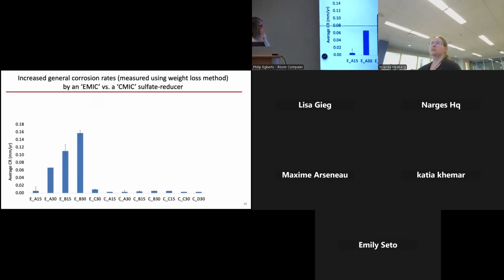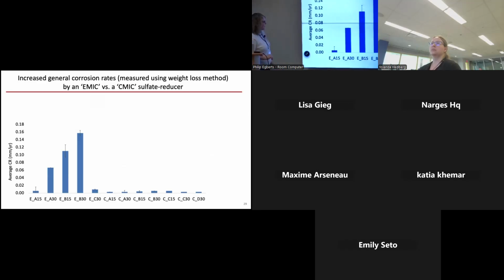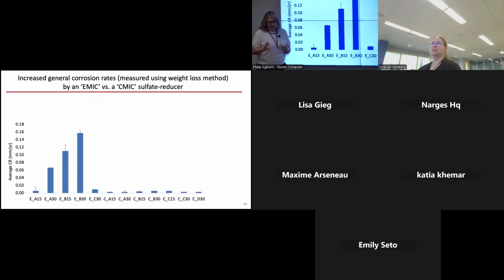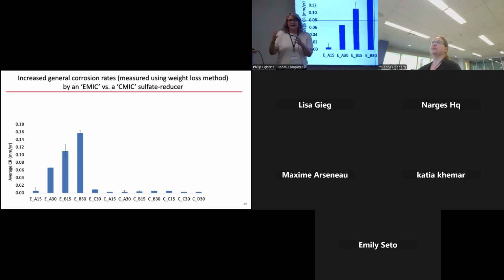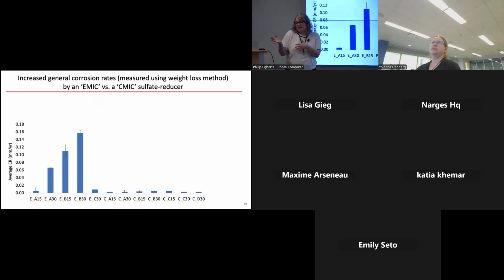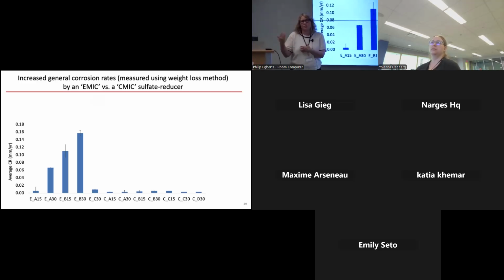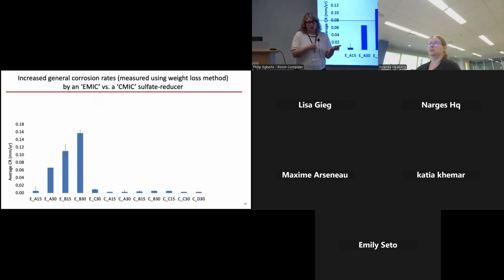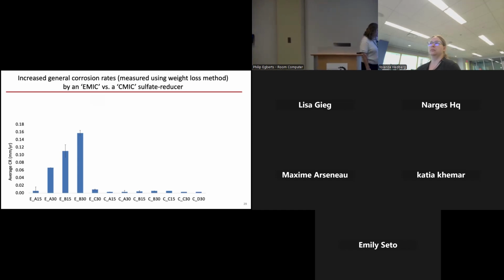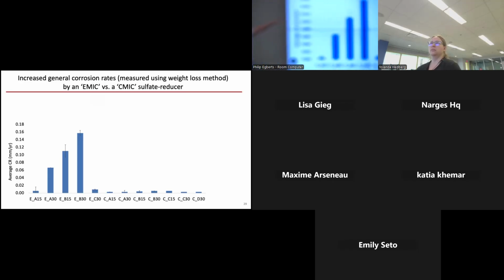I wanted to show you one example of an experiment we did quite a long time ago. We were looking at corrosion rates by an EMIC sulfate reducer, so we expected the corrosion rates to be higher, versus a CMIC organism where we expected the corrosion rates to be lower. On this graph, we have average corrosion rates, and each of these little names at the bottom are different cultures. These blue bars are different corrosion rates that we obtained from our EMIC organism.